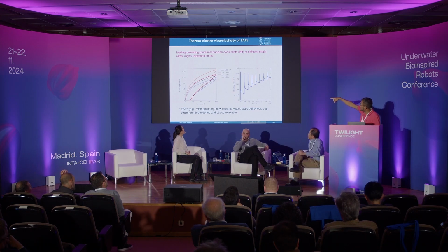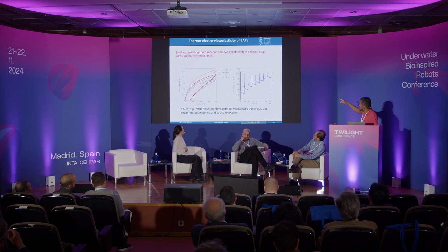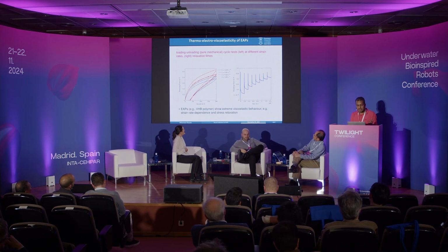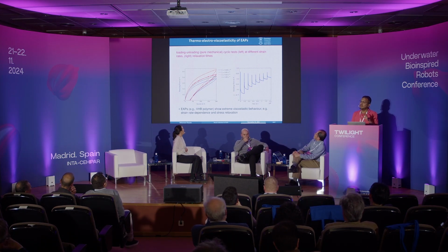And then you see rate sensitivity, right? Different strain rates, and you are getting different responses. And then if you do the relaxation test, it has a significant amount of relaxation if you pull the sample and you wait for a couple of minutes, and then you will find the relaxed state. Okay, so this is about the mechanical test.